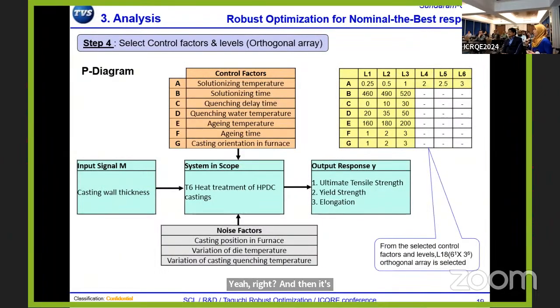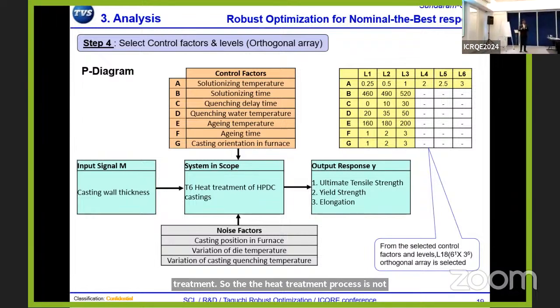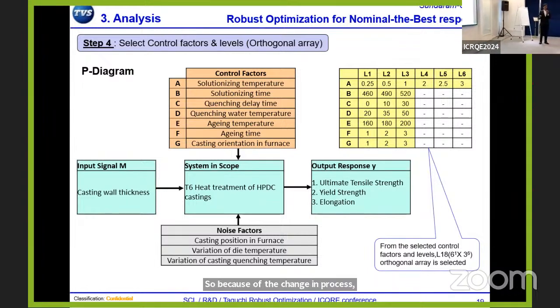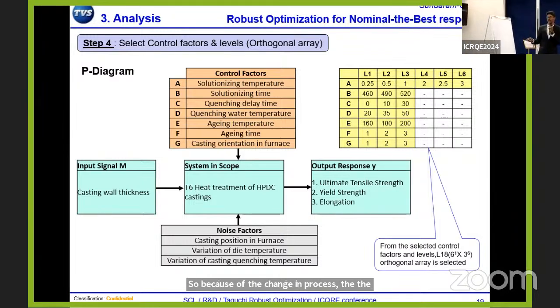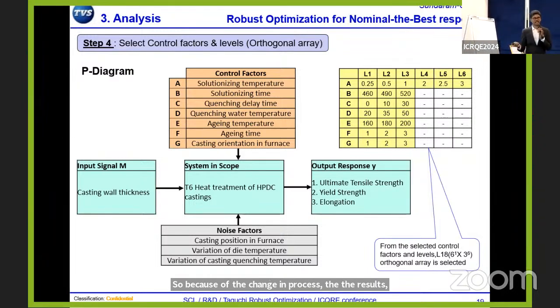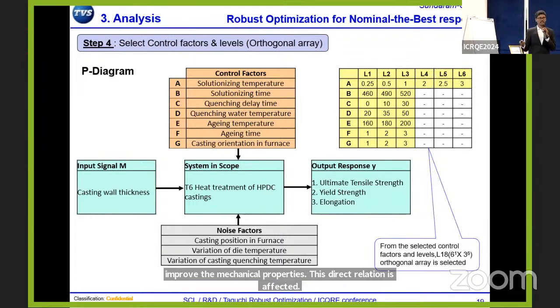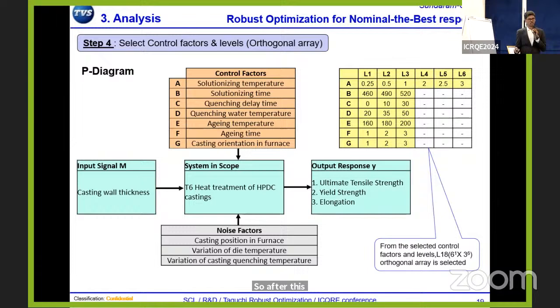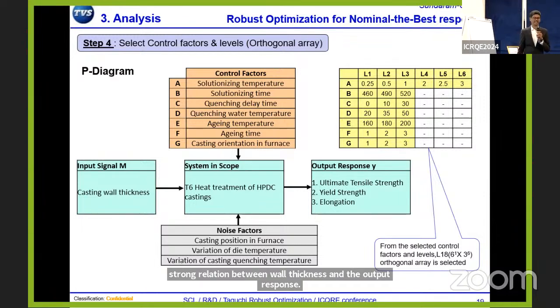See, before the start of this project, we thought that the wall thickness was contributing to strength based on the literature survey. But we are doing different kinds of heat treatment. So the heat treatment process is not constant for all L18. Because of the change in process, what we thought, that casting wall thickness will always improve the mechanical properties, this direct relation is affected. So after this study only we came to know that there is no strong relation between wall thickness and the output response. Okay, because it's a weak relationship. Yes.